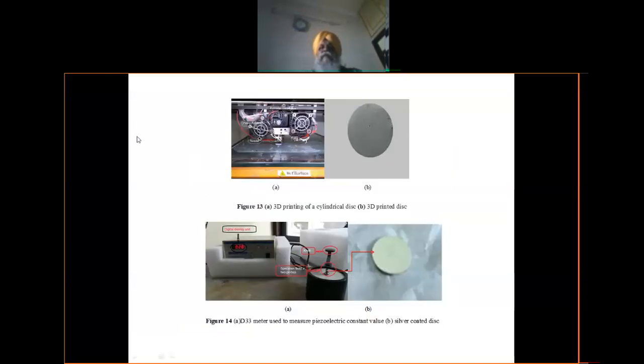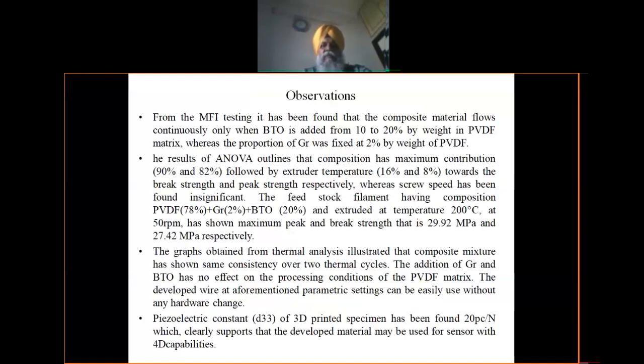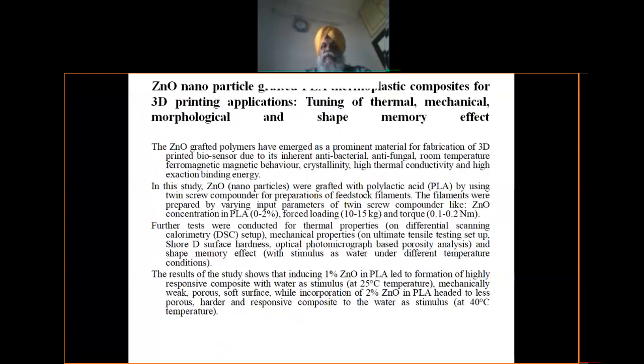Then that material was fed into the 3D printer. So I print different sizes of specimens. Then we measure the D33 effect to understand the piezoelectric constant. What we observed for this case was 20 picocoulomb per Newton. That was sufficient for giving me some sort of electrical signal to get it converted into some useful information, right? So this is 20 picocoulomb per Newton. That was really appreciable for us for developing a sensor with 4D capability.